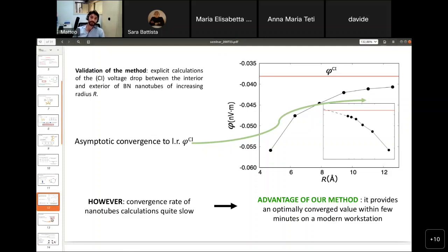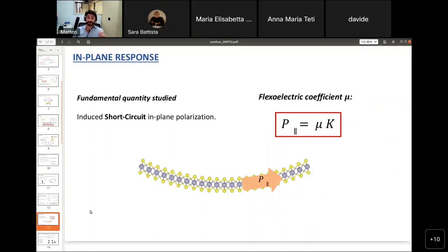So we just described the out-of-plane response, but actually we recently predicted an in-plane response. In this case, we describe the in-plane response as the short-circuit curvilinear polarization response induced by the curvature. So, similarly to what we did in the out-of-plane case, where we used the flexural voltage, and then the voltage drop response, here we define the constant mu, that is the constant of proportionality between the in-plane polarization and the curvature.